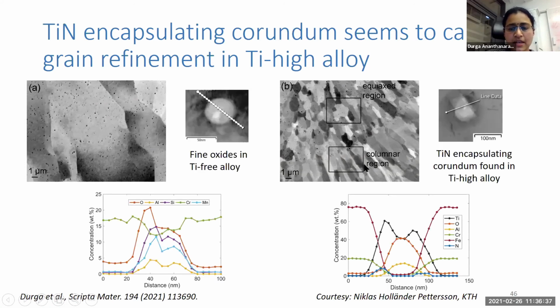A little bit more analysis confirming whether titanium nitride is forming. When we look at both the titanium free and titanium high material, both seem to have some particles in the as-printed structure. In the case of titanium high, we have bigger particles in the equiaxed regions, and in the slightly columnar regions that we found, we had very, very fine particles. My colleague Niklas analyzed this further and found that there were very fine oxides in the case of the titanium free alloy. And in the case of the titanium high alloy, we have titanium nitride encapsulating the corundum particles. That's what the compositions seem to suggest.